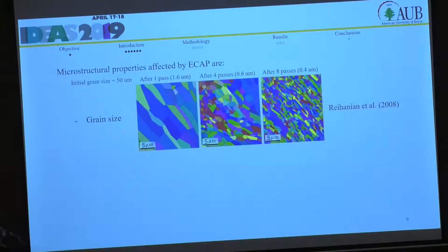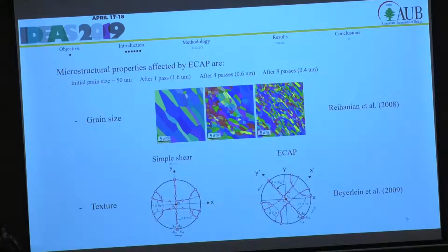And now we will see some microstructural properties that are affected by the ECAP. We have the grain size. We can see here that the initial grain size is reduced from 50 to 1.6 micrometers just by pressing it one time. And it's known that when we have smaller grains, that means higher strength. Another feature that's affected is the texture. The texture is the representation of the orientations of the crystals within the polycrystal. So the ECAP can reorient the ideal orientations of the lattices or of the crystals inside the polycrystal.